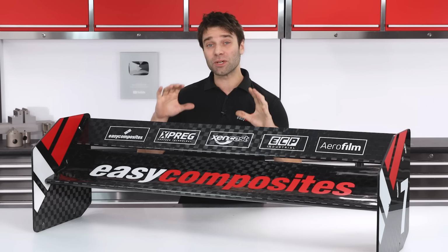We're now ready to bond this assembly together. The adhesive that I'm going to use for this will actually be made using the ER1 rapid repair resin. I'm choosing this resin because it has excellent adhesive and flexural properties, and it also cures very quickly for a resin system. But in order to make it appropriate for this application and change the viscosity, I'm going to first add some fumed silica.